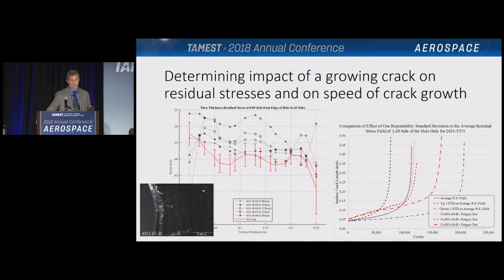The red lines show the growth of 3 cracks in test specimens, right here, these 3. And then the black lines are analytical comparisons using the average residual stress field as well as up and down 1 standard deviation to understand the impact of variability due to the measurement uncertainty. You can see that in this case, our max and min analytical comparisons do bound the 3 test results.